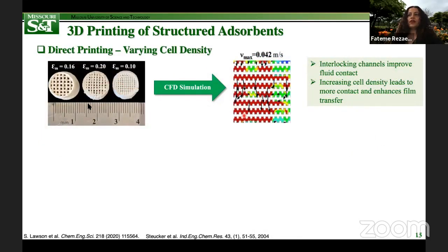Direct printing allows for varying the cell density of the monoliths and consequently fine-tuning their adsorptive performance. To achieve this, we previously synthesized zeolite 13X monoliths with 200, 400, and 600 CPSI, or cells per square inch, and investigated their dynamic adsorption behavior in CO2 capture process. From CFD simulations, interlocking channels improve fluid contact, and also we expect to see the increase in cell density leading to more contact and contact time and enhancing film transfer. However, we have found the opposite to be true for our monolithic structures.